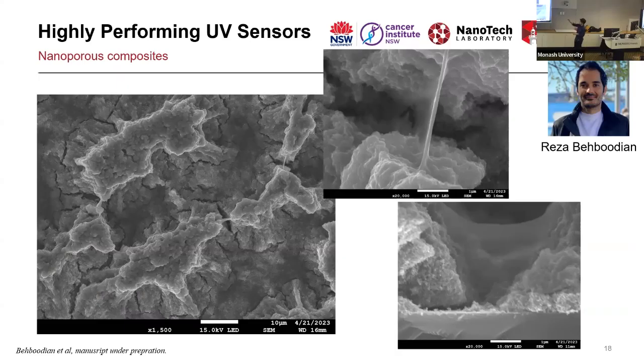In this work, which is not published yet, Reza added PEDOT:PSS as a polymer. Again, we could not add polymer into the system before because it would damage the structure significantly. But now, after modifying it, the second droplet could carry whatever material you want. As you can see here, this cluster is beautifully connected with the PEDOT:PSS, which is a conductive polymer, to the other one, and that one to the next one. Of course, there is a lot of optimization to make sure it is not too much polymer. Then we have all these clusters communicating with each other, both from the very bottom, this is the substrate, and also from the top with a very optimized thin layer of polymer.